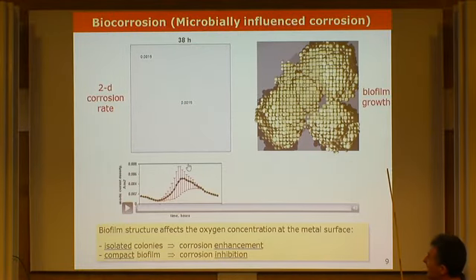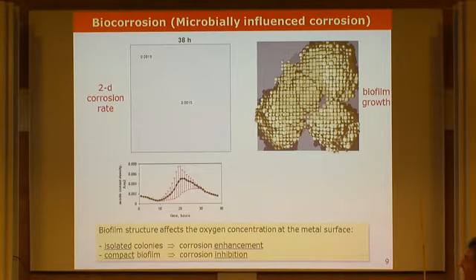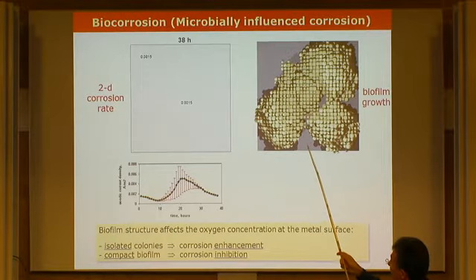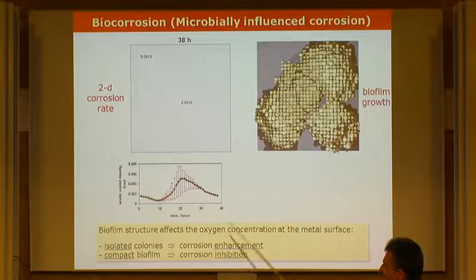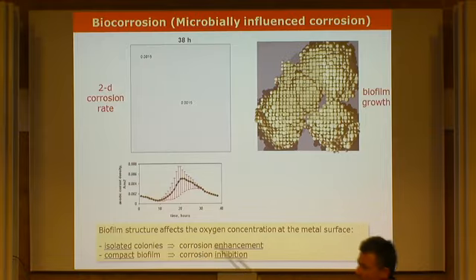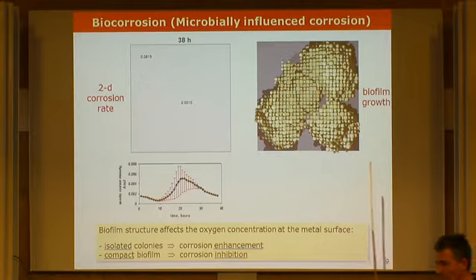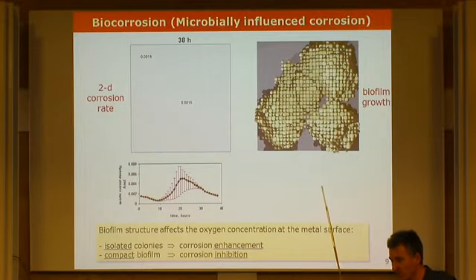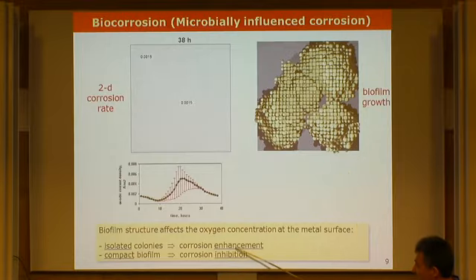And this is practically a project we had with the TNO. The Dutch people know this organization. They wanted to apply bacterial coatings to prevent corrosion, to mitigate corrosion. And there are people working in the world on these kind of topics. So practically, if you have a compact biofilm, you can have corrosion inhibition because you run out of cathodic space in this case. If you have patchy biofilm, so colonies here and there, you may have corrosion enhancement or pitting because you can balance enough anodic places for corrosion with enough cathodic space where oxygen is reduced. So this was kind of a nice finding in this piece of work, that practically biofilms, aerobic biofilms like these, can act in both ways, enhance or inhibit corrosion.